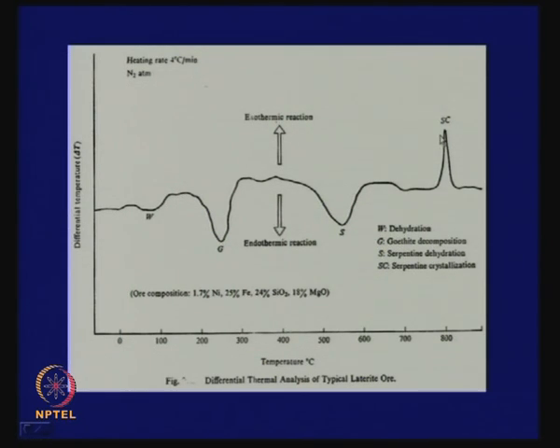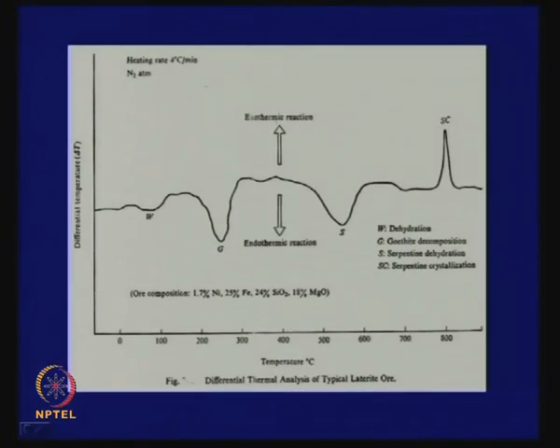Now, the next exothermic peak Sc at around 800 degrees represents the recrystallization of the magnesium silicate, which is liberated from serpentine, into olivine. It is Mg2SiO4. If this happens, then nickel oxide is locked up in that phase. The sum and substance is this: when you are heating a lateritic ore, water comes out, goethite decomposes, liberates NiO which was in the goethite, then the serpentine phase goes through decomposition and recrystallization. If that happens, then nickel oxide goes into that serpentine phase and becomes inactive again. It is not available for reduction. So, whatever we do will have to be done below 800 degrees. This is the sum and substance of that.